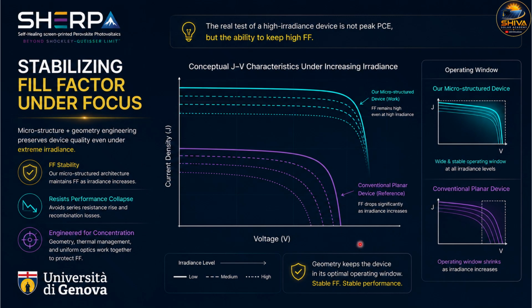But for the conventional planar device, which is shown in purple, the curve actually progressively collapses under higher irradiance. This is mainly caused by thermal stress, transport losses, and increased recombination. The operating window comparison on the right actually summarizes the difference, which is very clear. The microstructure architecture, as I said, this is not a real JV, but it follows this trend. This maintains a wider and more stable operating regime, while the planar reference rapidly loses its stability. So the key advantage here is not only the efficiency, it is operational robustness under extreme optical conditions.